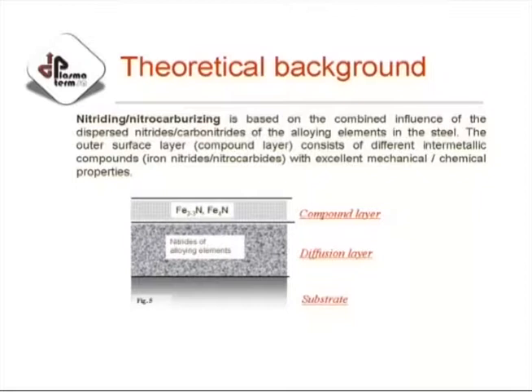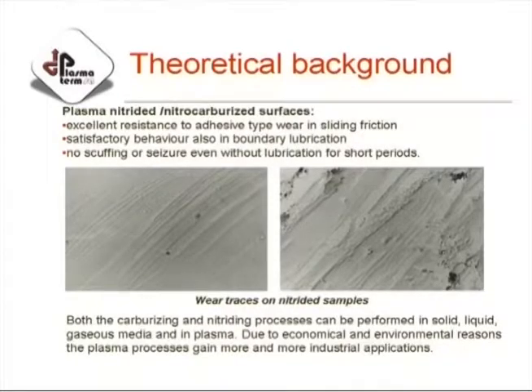So this compound layer, the nitride compound layer, epsilon or gamma dash compound layer, has an excellent wear resistance, and the wear of such a layer is completely different from the wear surface we have seen. Well, you see, this is a worn surface after quite a long running time. I shouldn't say how long. Well, you do not see this typical damage which I have shown on the other side. And this is at higher magnification in some places. You see the traces, but no scuffing or seizure occur.